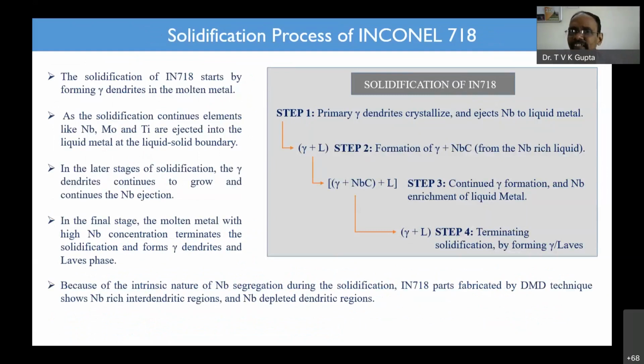Now, the solidification process, if you try to see, solidification of steels is something different. Solidification of nickel-based alloys is something different. In the solidification of steels, you will get only martensite, cementite, or pearlite, whatever structures you get in iron-based alloys. But in nickel-based alloys, there will be different phases which you are going to see, like elements such as niobium, molybdenum, titanium. So in the solidification of 718, it starts with gamma dendrites and it is going to eject niobium into the liquid metal. So that is the first step.